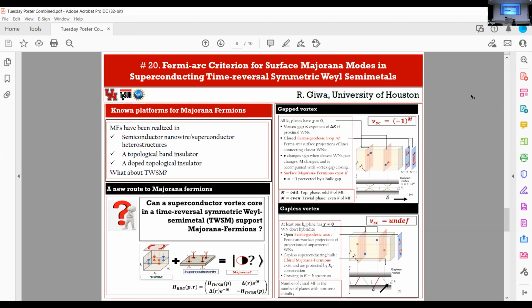So in this work, we show the condition for which we can find surface or chiral Majorana fermions, namely that it depends on the Fermi arc structure, the proximity of the Weyl nodes, the net chirality and the vortex orientation. We predict a gapped vortex if the net chirality in each kz plane is 0. Otherwise, we predict a gapless vortex if the net chirality in each kz plane is non-zero. In either case, we can have surface or chiral Majorana fermions emerging either at the surface or the bulk of the superconductor.